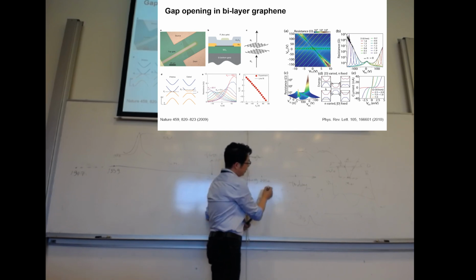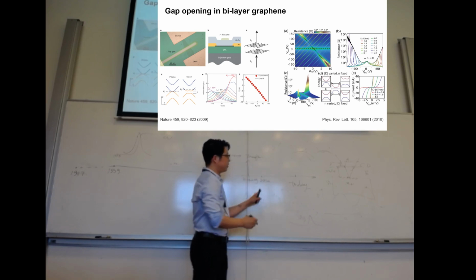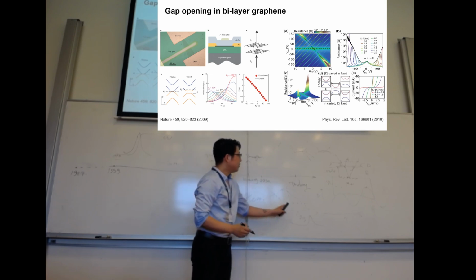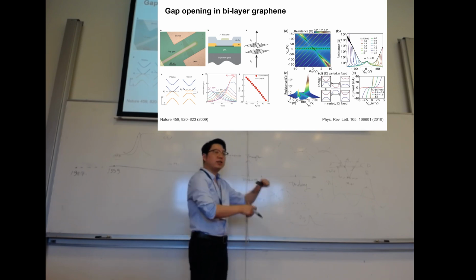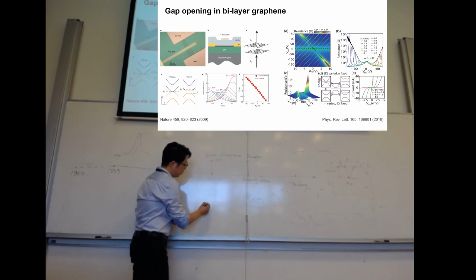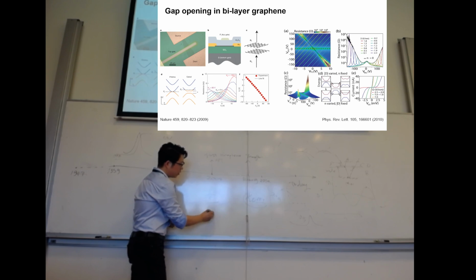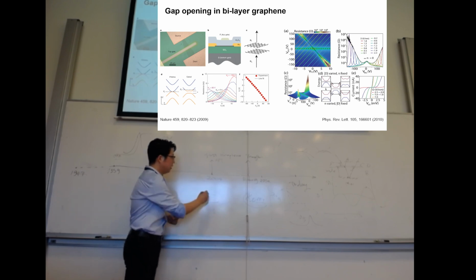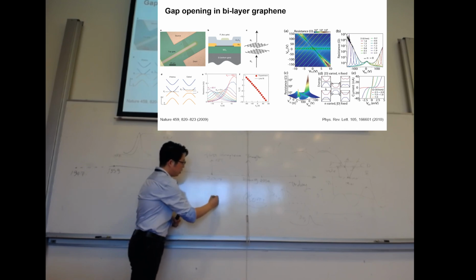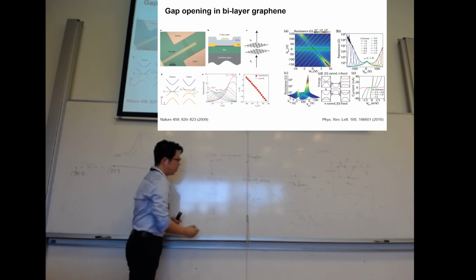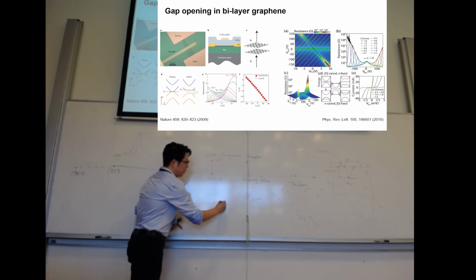If you make a line cut from here, you get a top gate dependence resistance peak. And here there are two gate voltages acting together on your graphene. So this is a bilayer graphene. There's a dielectric on top, there's a dielectric on the bottom, there's a metallic plate on top, and there's a metallic plate on the bottom. And this guy is grounded.